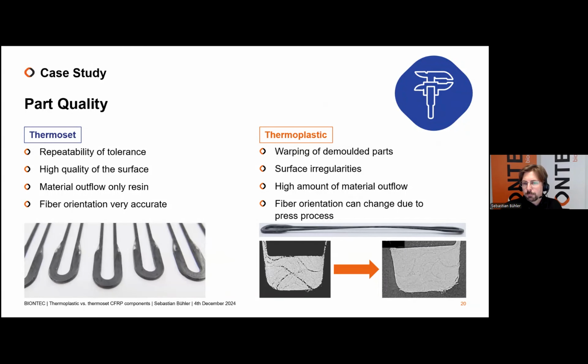We want to have them later in the part as we have designed it. And below you see a picture. When we started with the process, we see here in the picture the resin outflow at the top, and we have not gained enough overfilling and not enough pressure, and we see some voids here. So the consolidation is not so good. At the end of the project, and for all the thermoplastic parts we do today, we have a cross section like this on the right side here. Here we have no voids anymore. It's a perfectly consolidated cross section.